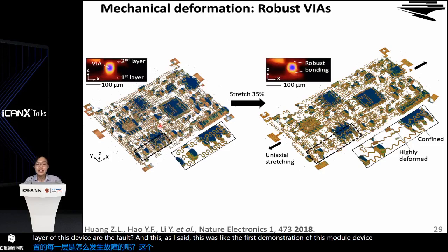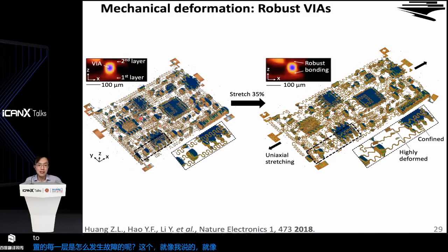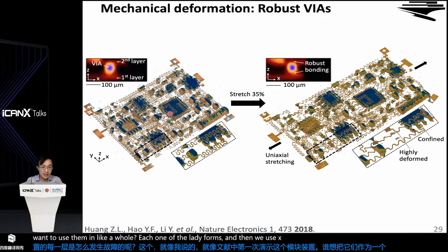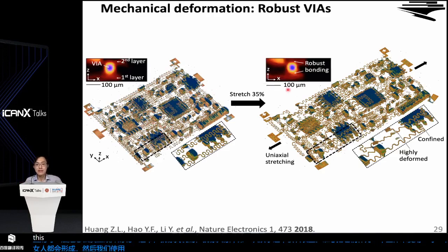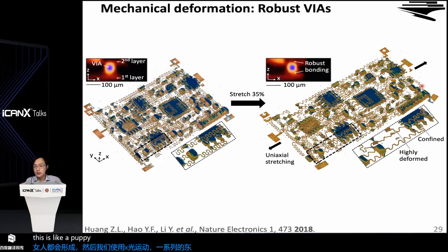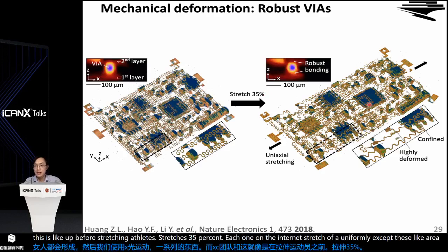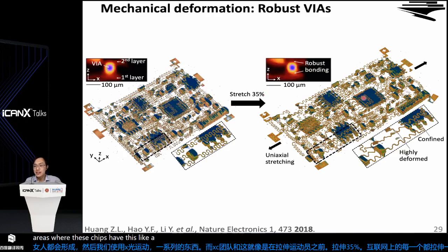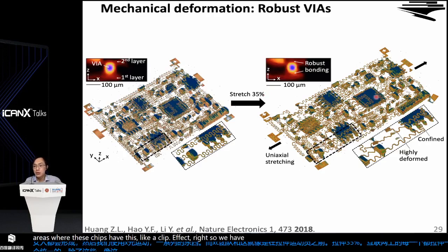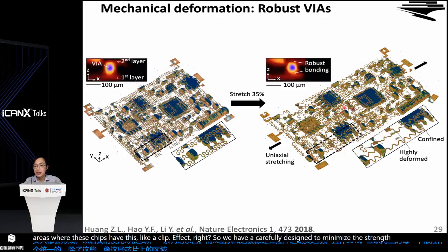We want to examine how each one of the layers deforms. And then we use X-ray. X-ray can penetrate a lot of stuff. And this is XCT, and this is before stretching, after it stretches 35%, each one of these interconnects stretches out uniformly, except these areas, where these chips have a clamping effect, right? So we have to carefully design to minimize the strain between this rigid chip and the soft surrounding matrix.